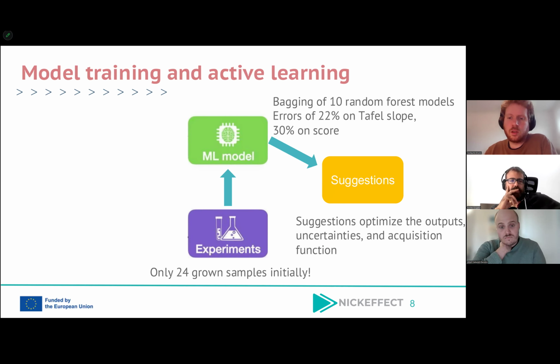for the deposited film. Another type of suggestion is also based on the model's uncertainties. So with the prediction of the model, you also have a measure of how sure the model is of itself, kind of an error bar on the prediction of the model. And if you provide suggestions where this error bar is the largest, and then these are done in the lab, you really reduce the uncertainty of the model in the most optimal way. So that in that way you optimize the model before optimizing the output. And then there's also a trade-off between the two. It's called using the acquisition function, where you optimize both the output and the uncertainties at the same time.